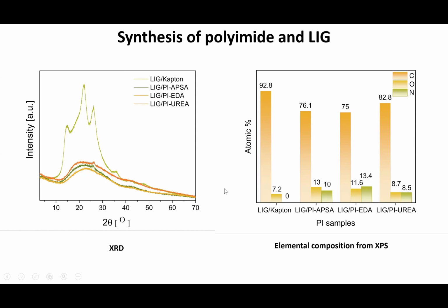We performed XRD again, shown on the left. The big, yellowish or greenish curve is from Kapton. Kapton is a semi-crystalline polymer, and that's why you get these different peaks due to the crystalline structure. Our polymers are cross-linked polymers, which means they're amorphous. So you get this broad amorphous halo, and on top of that, you get these very small peaks, roughly at 26 degrees, which correspond to graphene.